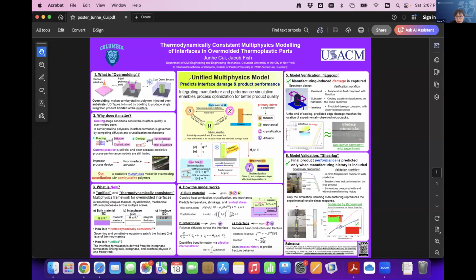So let's now start with the motivation. What is overmolding? Overmolding is a manufacturing process where hot polymer melt is injected onto an existing substrate and then cooled down to form a single integrated component. It's attractive for lightweight composite manufacturing because it offers an efficient way to make high-performance structures, such as automotive panels and aerospace interior parts. But the key issue is the interface, because the final product's performance depends strongly on the quality of the interface. However, it is very hard to predict the interface.